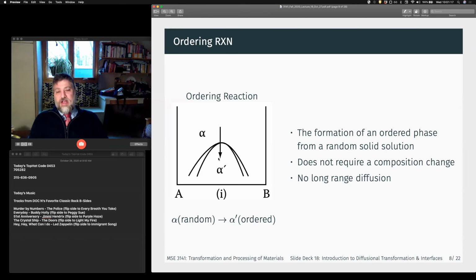Now, the important thing to realize about this transformation is it doesn't require long-range diffusion. We still require diffusion because we have to swap atomic positions, but it's only diffusing over short range. We only need our atoms to move over a couple atomic positions. We do not need them to go long range, and there doesn't have to be a local composition change, right? So that's the big distinction, right? Because it doesn't require long range diffusion, it's very difficult to stabilize the random disordered solution at lower temperatures, right? It's going to have a tendency to order even at lower temperatures because we don't require long range diffusion and we don't require a composition change, right?